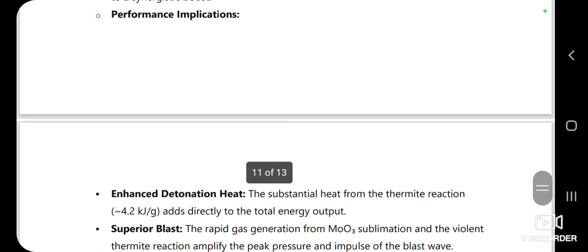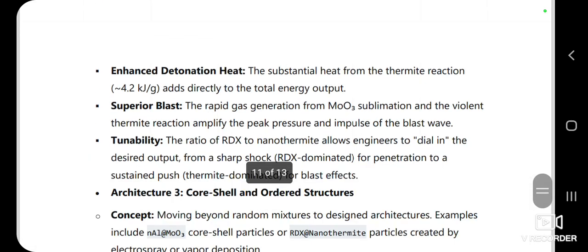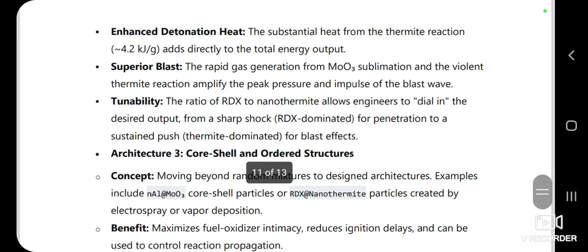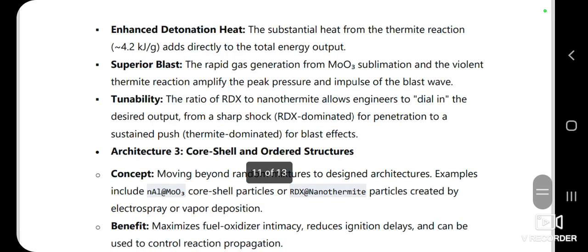And what are the performance implications in this case? It enhances detonation heat: the substantial heat from the thermite reaction, about 4.2 kilojoules per gram, adds directly to the total energy output. Superior peak blast: the rapid gas generation from molybdenum trioxide sublimation and the violent thermite reaction amplify the peak pressure and impulse of the blast wave.